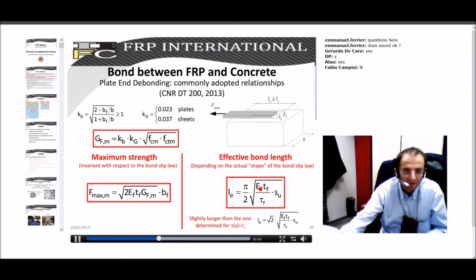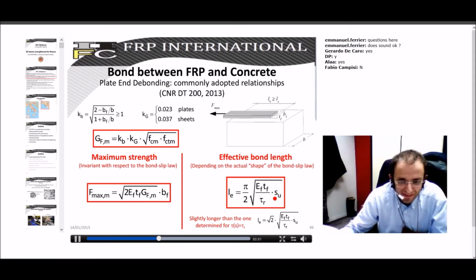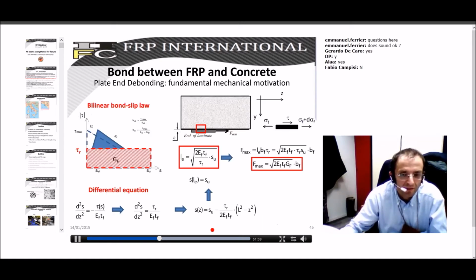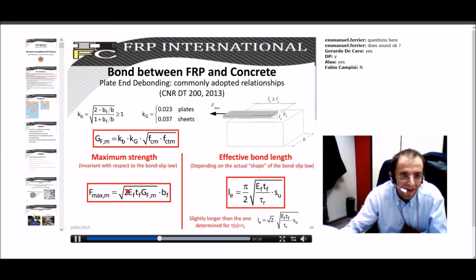You have to expect to find EF, TF at the numerator, you have to expect a square root, you have to expect something related to the ratio between the maximum shear stress and the maximum displacement, but this number depends on the shape. So you have pi divided by 2 in the case of a bilinear relationship, or radical 2, as we have found for a constant tau S. So this one is valid for any tau-slip shape. This one, especially this coefficient, theoretically depends on the shape of the tau-slip relationship.